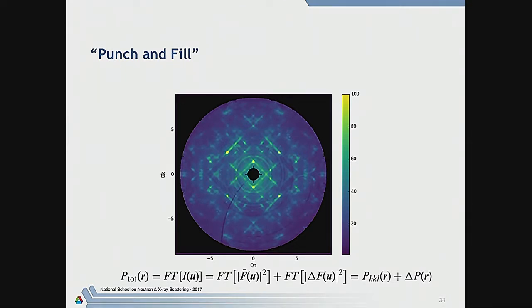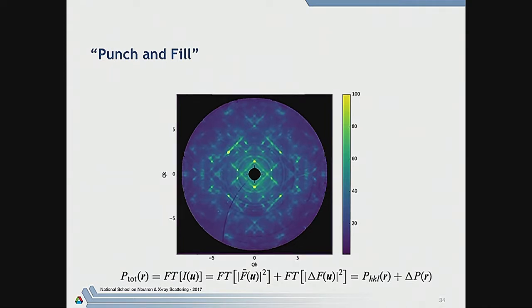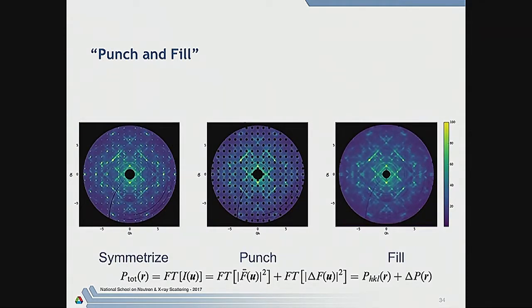So now we have a three-dimensional volume S(Q), which only contains the diffuse scattering, which represents deviations from the average structure. Okay. Now this is a full three-dimensional volume. Sometimes we don't have all the data we might need, so we might need to do some symmetrization to fill in some gaps. But on the whole, with our three-dimensional technique with X-rays anyway, and as I'll show later with neutrons, we can actually fill in those gaps very well.